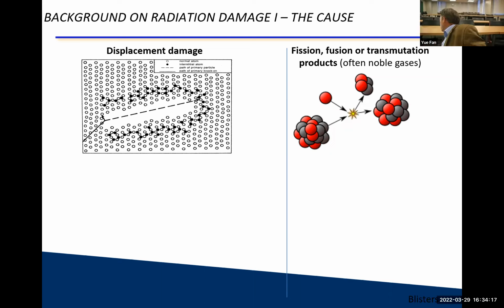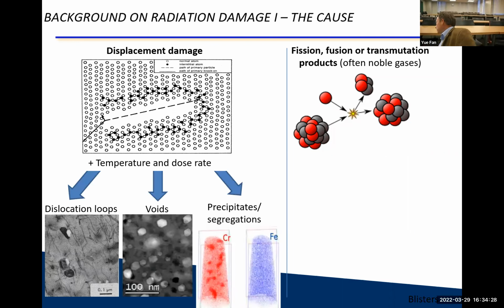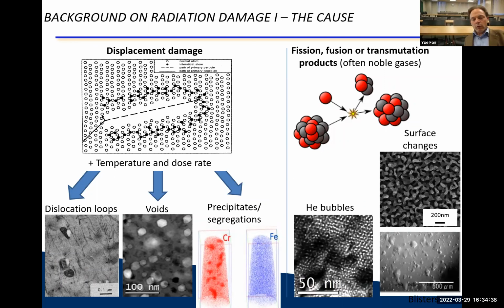But you can also have transmutation products. So you can have your atom being transmutated into other elements, being helium or other things. And so that's also something to consider. Now, the displacement damage leads to dislocation loops, maybe voids, maybe segregations, precipitate forming, these kind of features. Versus transmutation products or gaseous products, which oftentimes can lead, in the fusion world, to fuzz formation on the surface, or helium bubbles building up in the material, or blisters forming underneath the surface. So those are very different phenomena that can happen, right?